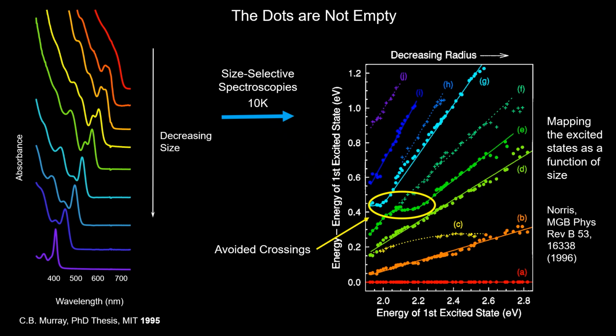And as a spectroscopist or a physicist, you look at that and you say, wow, this tells me something really fundamental. And what it is telling you is that at this point, that electron, that wave, is actually seeing that the box has atoms in it. It's not an empty box. It's a box full of atoms. And that electron and those atoms form a periodic lattice. And now that electron scatters off that periodic lattice, and that is the spin-orbit coupling that you are seeing there, the spin-orbit coupling of that semiconductor that's appearing, which was not there at the smaller particles. This is a transition. So every property has a transition at a different size, right? And this is the size for that property.